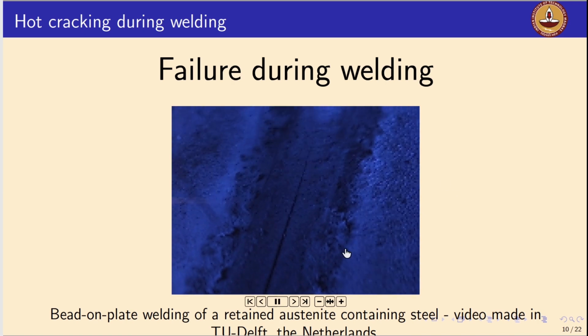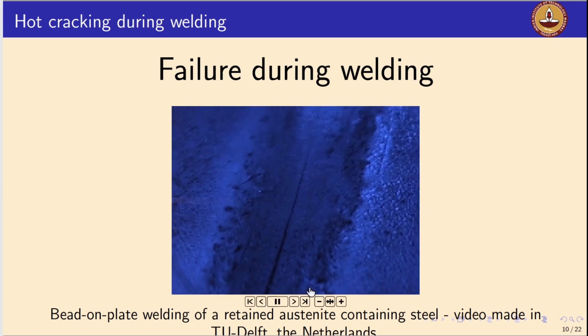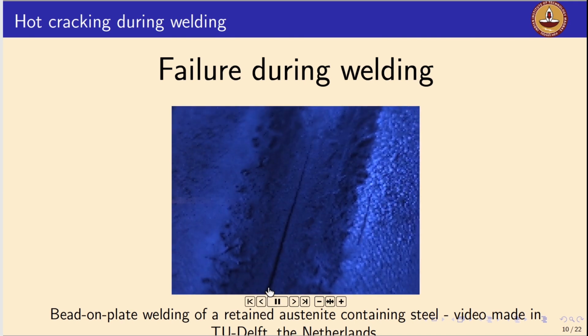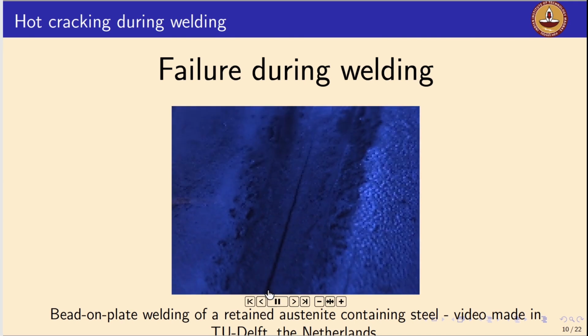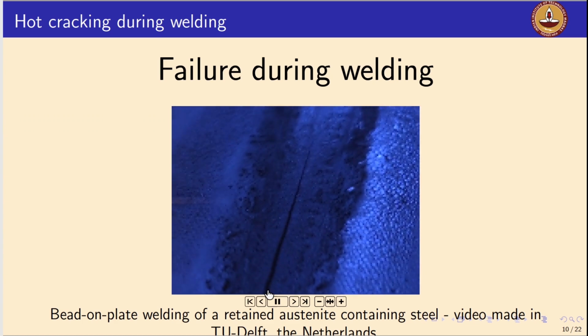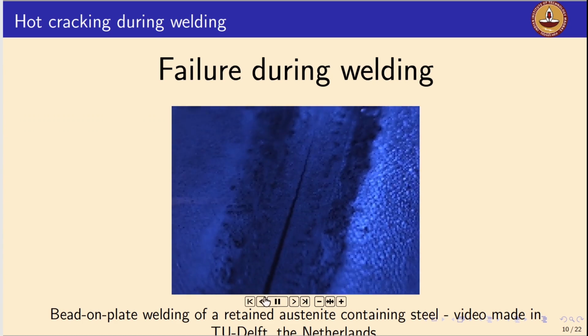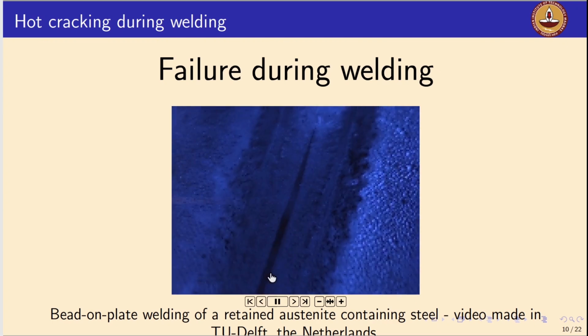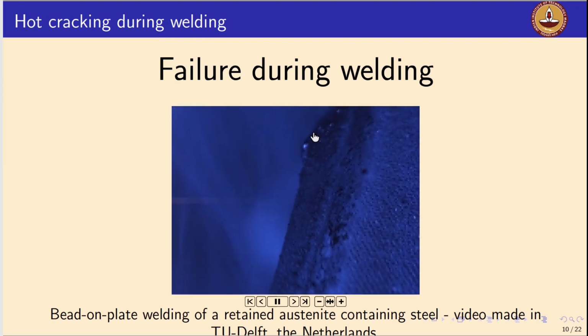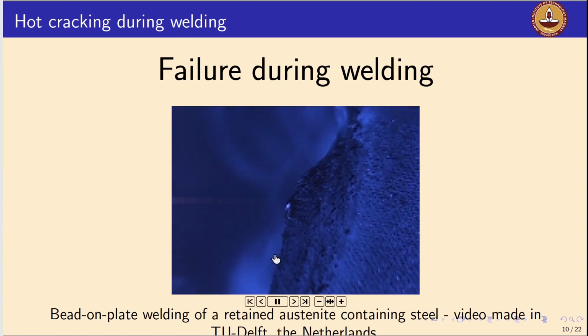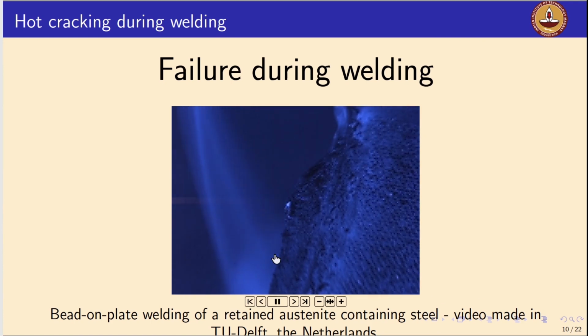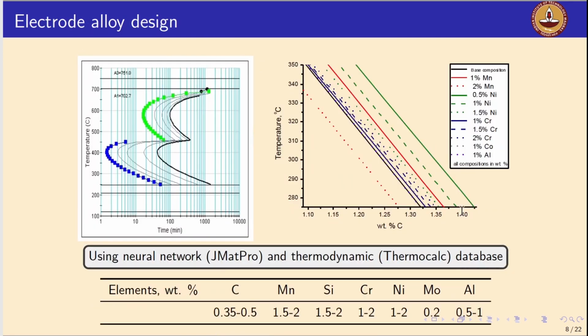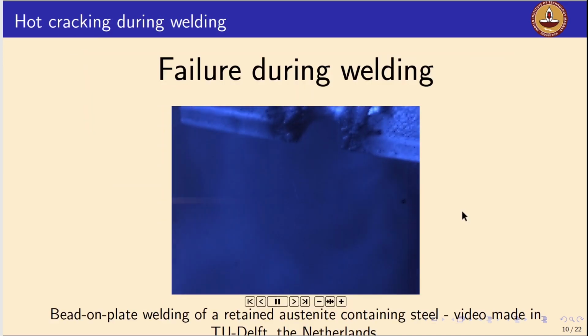So one such weld is actually shown in this video, where we are doing a bead on plate on a retained austenite containing steel. So instead of actually welding, we are actually cutting. This cutting, what you see over here, is nothing but a hot crack, which is forming and progressing continuously. Instead of welding, we are actually breaking the weld as a cut, right? And this is a not optimized condition, right? So from the identified candidate chemistry, if we straight away start doing welding, we have a problem, isn't it?